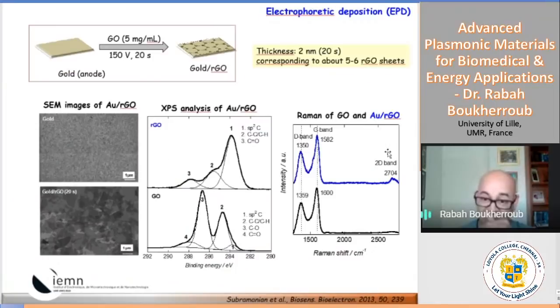Okay, so this is just graphene. You can see it takes about 20 seconds. I can transfer about 5 to 6 layers, and I can transfer and reduce the graphene oxide at the same time. And I can limit it to 5 to 6 sheets, not more than that. Well, if you look at the XPS, of course, it tells you that the graphene, when it's transferred, is also reduced at the same time, but you have a lot of defects because chemically derived graphene is full of defects at the edges.